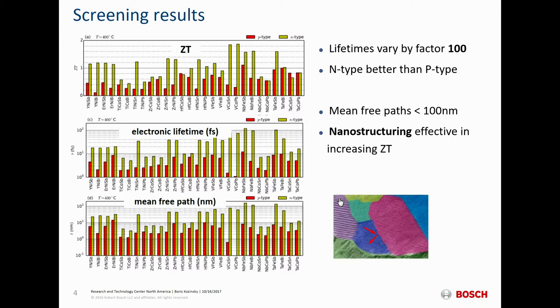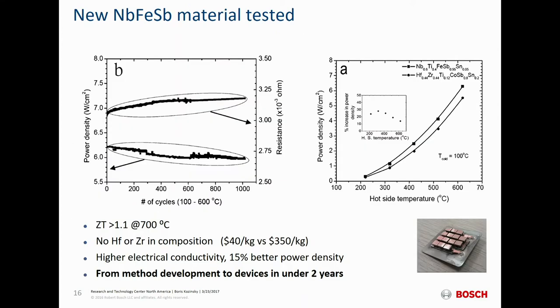We predicted a bunch of materials and a few months later our experimental partners synthesized a few of them. A new alloy — niobium iron antimonide — was synthesized and shows better power density than the state-of-the-art half-Heusler material known until that discovery. More importantly, we reduced cost from $350 per kilogram to about $40 just by removing hafnium and replacing with cheaper elements. The turnaround time was under two years for method development, screening, and a few months for experimental synthesis. This is an example of how you can rapidly get better materials with more predictive tools in your toolbox.